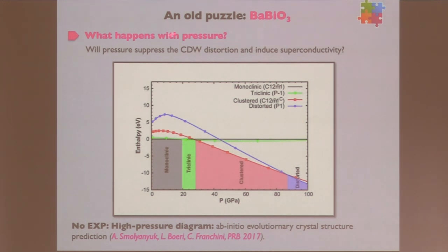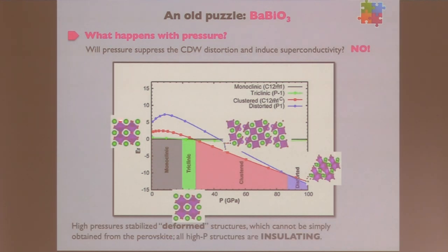This is BaBiO3, so this is barium bismuth O3. You see, you start from the low pressure regime. I mean, you have the correct sequence of transitions, like experimentally the transitions are known more or less until 25 GPa. And then we were expecting that this distortion would be suppressed and that we would recover some sort of more symmetric perovskite phase, what we actually found were a lot of unexpected structures, which are shown here. So you see, you go from this structure where you have breathing and tilting to some other structure where you also have breathing and tilting to some really strange structure which we call cluster,